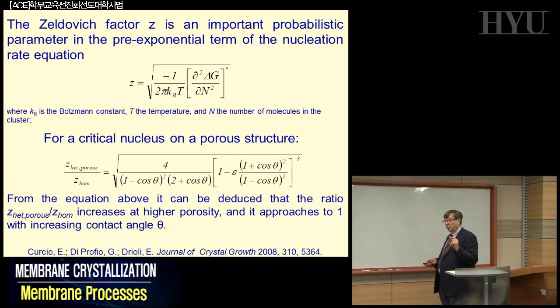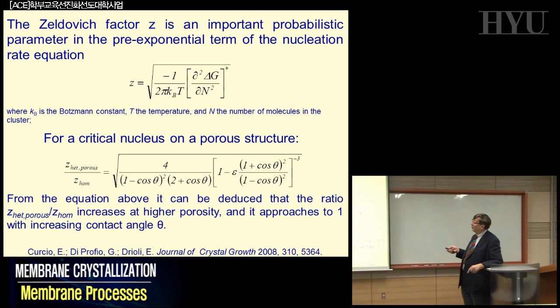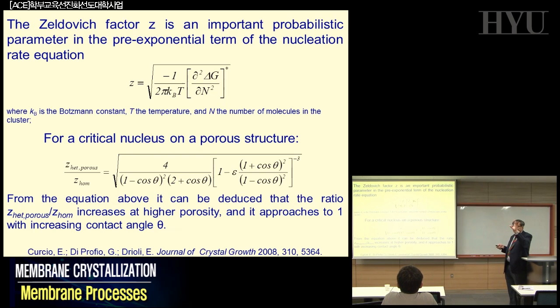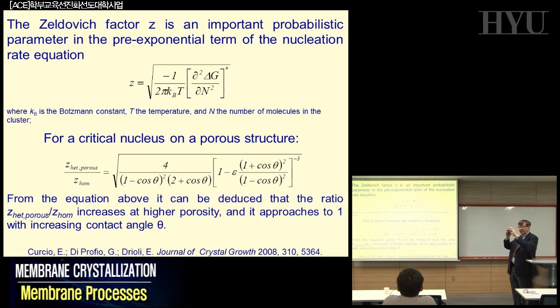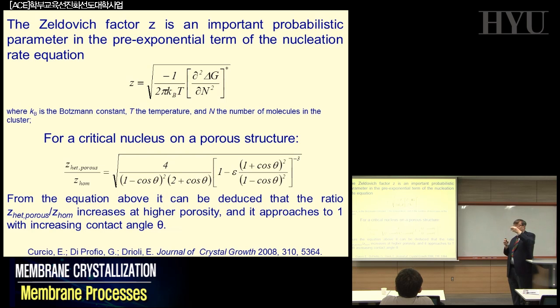There is another interesting aspect in which membranes have a role. One way to predict, to try to understand how the different molecules, nuclei, interact with each other, and after that produce a crystal, is to introduce some probabilistic parameters. This Zeldovich factor zeta is a probabilistic parameter, a statistical analysis that is telling you when you have already some molecules that aggregate, they meet together, and another one is arriving. The other one that is arriving can still interact or can be rejected. And depending on how this system works, you can make some statistics, some probabilistic analysis, and at the end you have this pre-exponential term of the traditional nucleation rate equation.